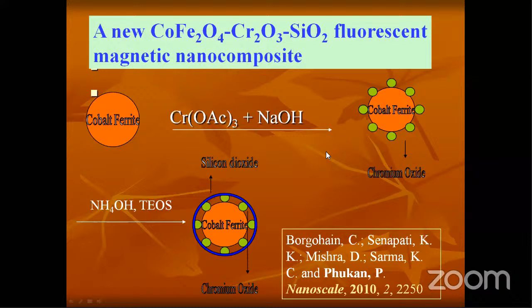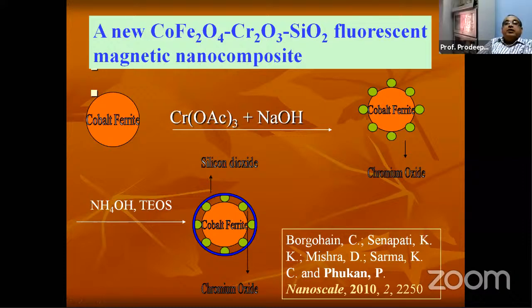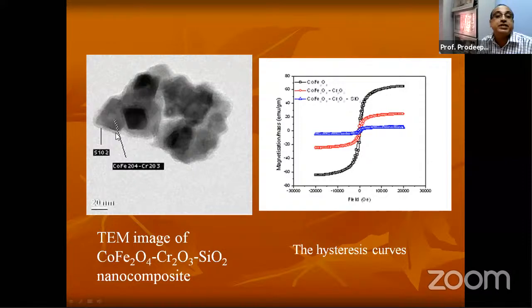And then we started changing our focus to synthesize different types of cobalt ferrite nanoparticles. So when we took cobalt ferrite, then put chromium oxide here, then we coated with silicon dioxide. First we made the cobalt ferrite, then we put chromium oxide on the surface, then we covered the surface. Interesting property we got. The surface is covered by SiO2, very clearly seen in the TEM picture.